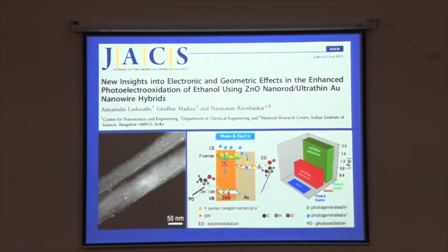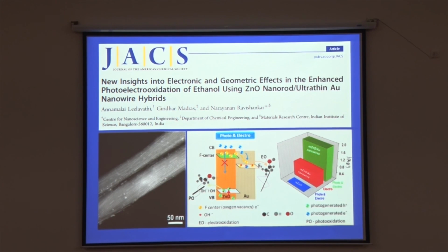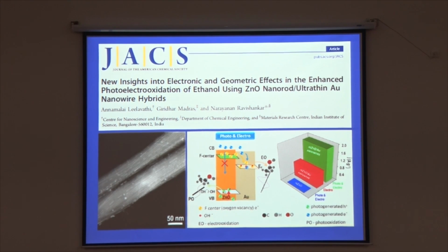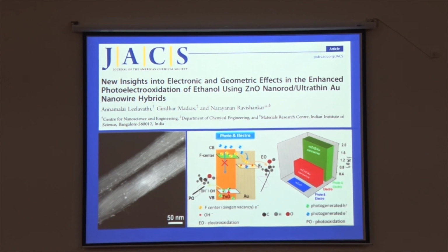One of the interesting things that is more recent that we have been able to do is to put them on something like zinc oxide, for example. This is an interesting system because if you shine light on zinc oxide, we get electron hole pairs, and the electrons can be transferred to the gold wires because of the suitable alignment of the energy bands, and that leads to very interesting enhanced photoelectro-oxidation of, for example, ethanol in this particular case.